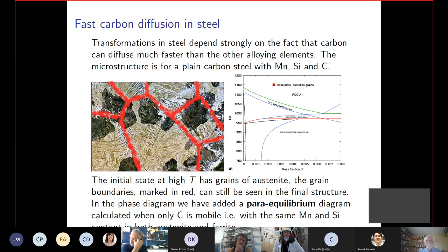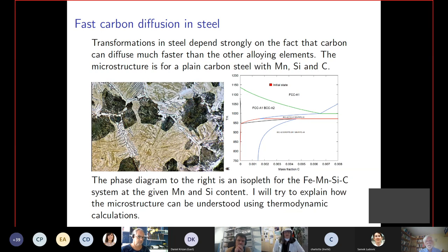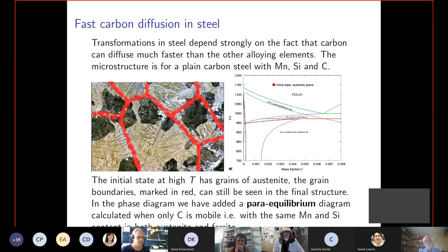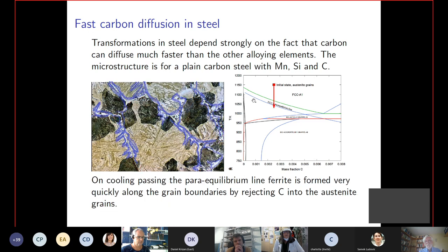And you can see in this microstructure there are some remains of these lines, which are the remains of the austenite structure you had at high temperature. This was the initial state. So initially at high temperature here, you would have austenite with grain boundaries like this. And when you cool it down below here, you will see ferrite forming along the grain boundaries. And those are the light structures you have here. I tried to emphasize where you actually get the ferrite forming. It forms first in the grain boundaries, because there you have a disordered structure.